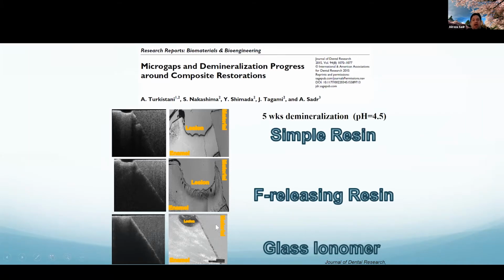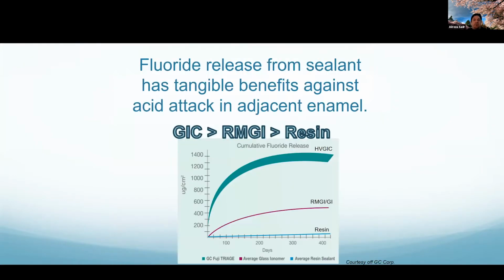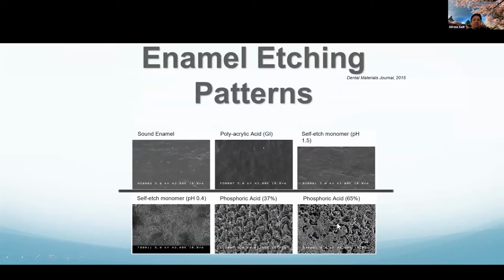Now, I don't want to say that you should fill all the teeth with glass ionomer. That's not the point here. But what I'm trying to convey is if you're sealing enamel, you want to use a sealant that also has beneficial release of fluoride and antibacterial properties, okay? So glass ionomer, if you have high viscosity glass ionomer cement, they have a higher release of fluoride. We know that from GC data, glass ionomer versus resin, right?